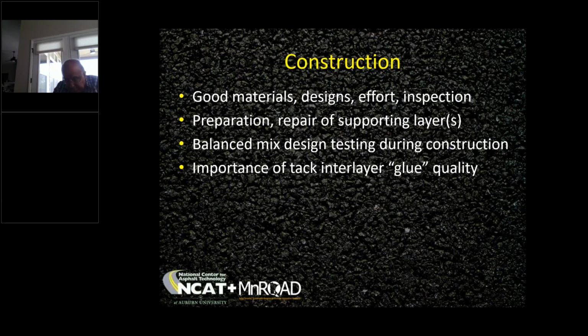We learned a lot at the track about the importance of tack interlayers, the glue that holds everything together. You can build a good pavement, but if you don't glue the layers together right, and it separates, it debonds at the layer interface, well, now you've got a thicker pavement that's going to behave like a really thin pavement, and it's going to crack, and performance is going to be very bad. So tack quality is very, very important.